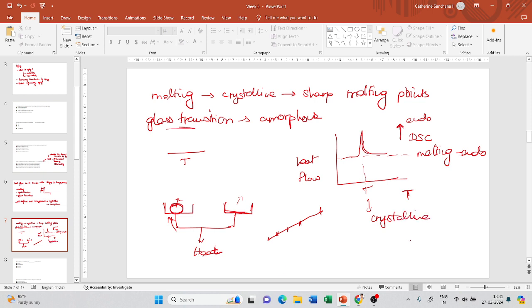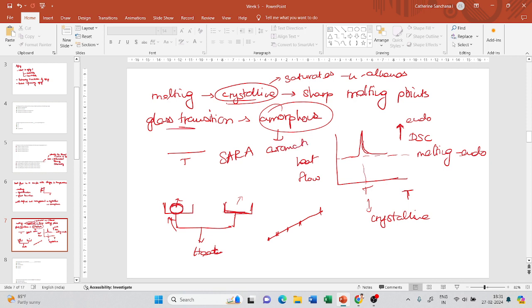But our bitumen will have a combination of crystalline and amorphous substances. We saw the SARA fractions in bitumen, where the crystalline fractions are associated with the saturates, which are mostly n-alkanes, and the amorphous components are due to the aromatics in bitumen, right?